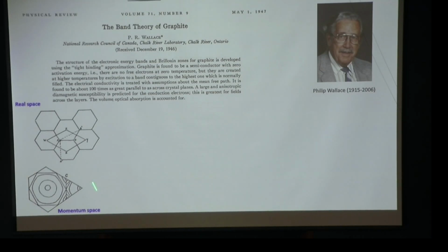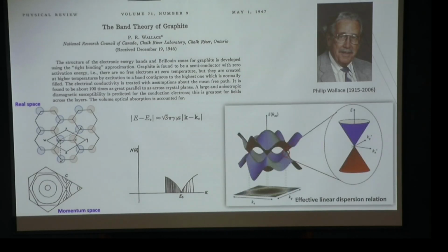For example, if you have the real space hexagonal graphene lattice, in the unit cell there are two carbon atoms, and the triangular shape. Then the momentum space description of the Bloch electrons to form the band structure is hexagons, and the corner points are interesting. Importantly, when you put two carbon atoms per unit cell and do the band calculation, Wallace found that the energy dispersion near the charge neutrality point of graphene is interesting, with a vanishing density of states and the dispersion linearly dispersing. If you look at the band structures, near this crossing point of the density of states at charge neutrality, the dispersion relation is strictly linear, like the following.